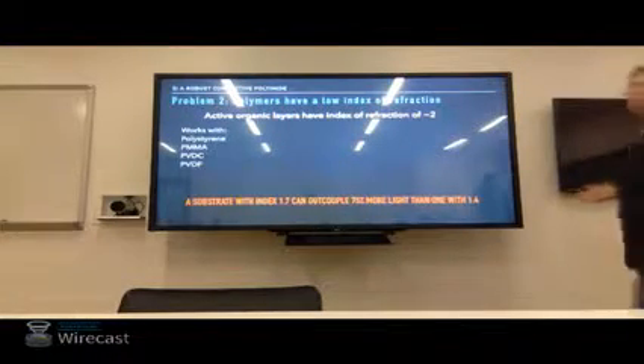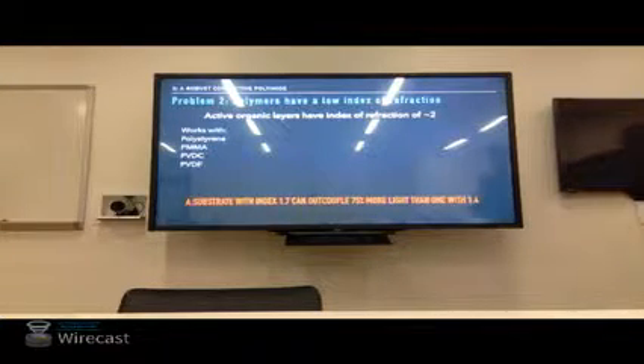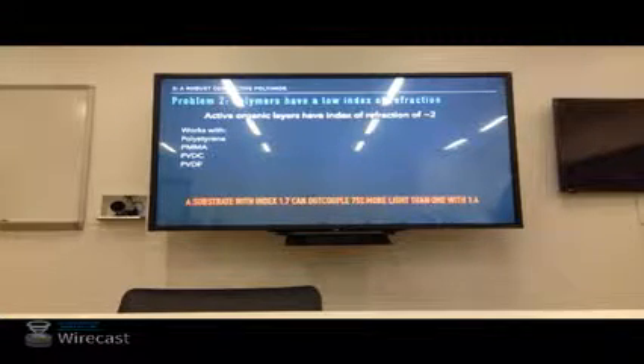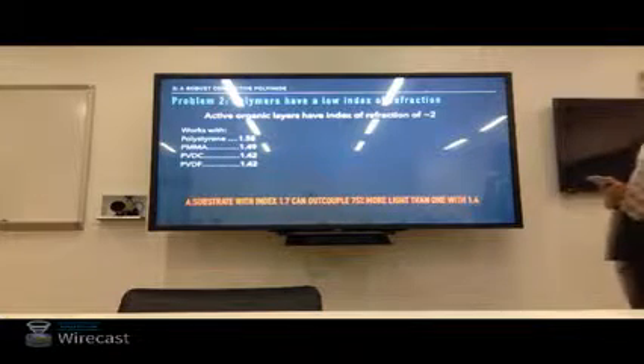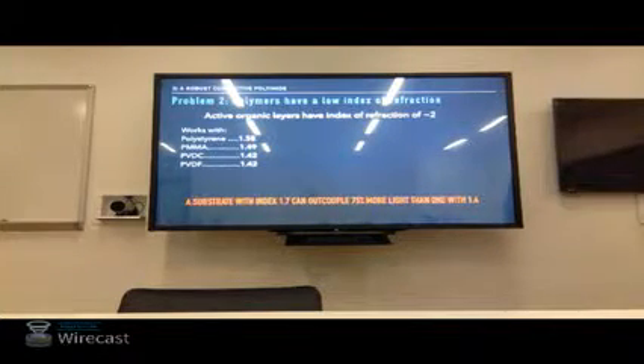This solution, of course, leads to problem 2. Problem 2 is that polymers have a low index of refraction, and the active organic layers in our device have a high index of refraction. This is the list I gave you on the last slide, works with these materials. Well, if we look at the index of refraction for these materials, say we're around 1.5.